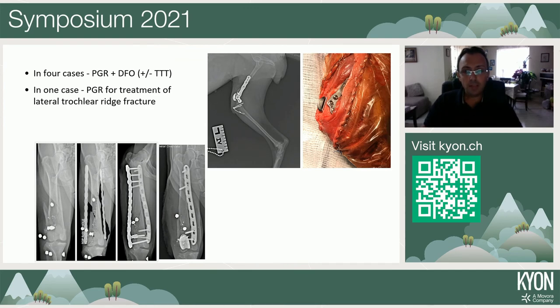In 4 of our cases, we combined patella groove replacement surgery with some sort of femoral osteotomy. Most of the time it was a distal femoral osteotomy to correct a distal femoral varus, with or without tibial tuberosity transposition. In one case, PGR was used to treat a traumatic gunshot fracture of the lateral trochlear ridge of the femur. In this case, we stabilized the fracture first because we were concerned about possible bacterial contamination, and then we went back and inserted the PGR implant.